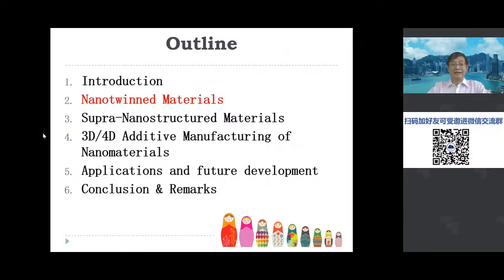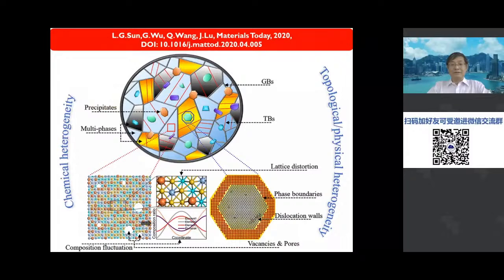So the first example I want to show today is nanotwinning materials. As you know, the main objective of structural materials is how to manage the defect or heterogeneity inside of the material, especially true for the metallic material. So basically, we try to manage the chemical heterogeneity, such as the precipitate, multiple phase, or topological or physical heterogeneity, such as the grain boundary, twin boundary. And in terms of chemical heterogeneity, if we go down to the atomic level, we can also manage the composition fluctuation locally, and also we can generate vacancy and manage pores at atomic level.